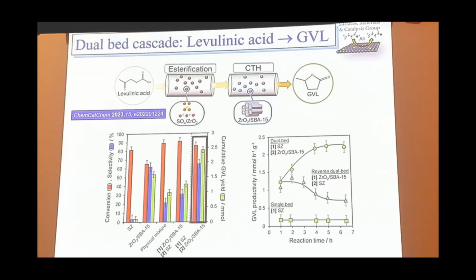And what we believe is happening, again, it comes down to really side reactions: if you put levulinic acid over the zirconia SBA-15 sample, you'll end up with other pathways being activated. So the take-home message really is that we can work these cascades in dual bed in order to optimize process efficiency.